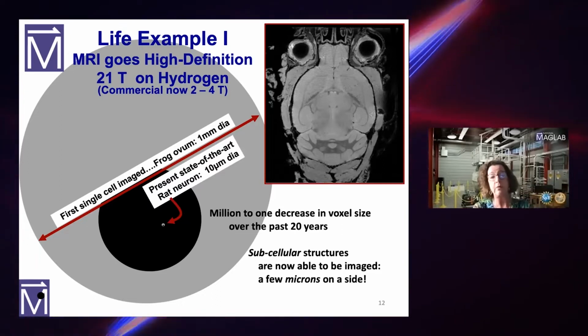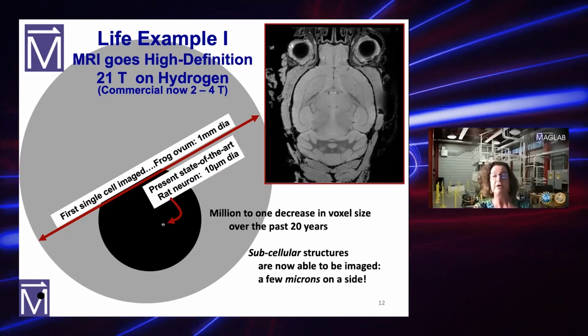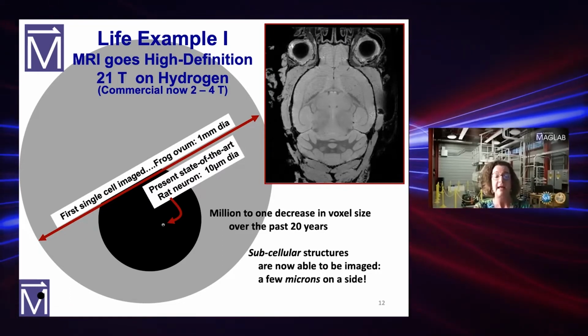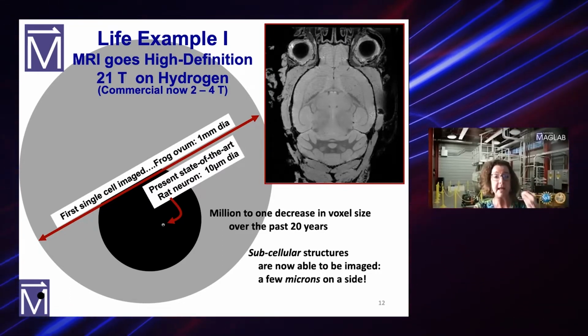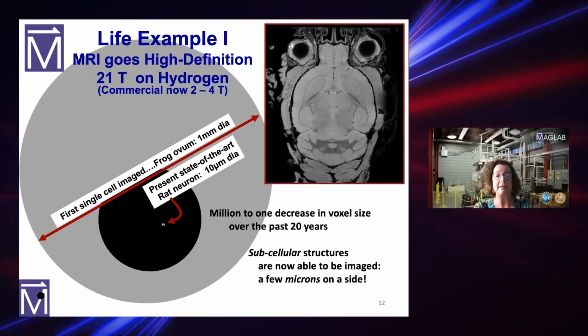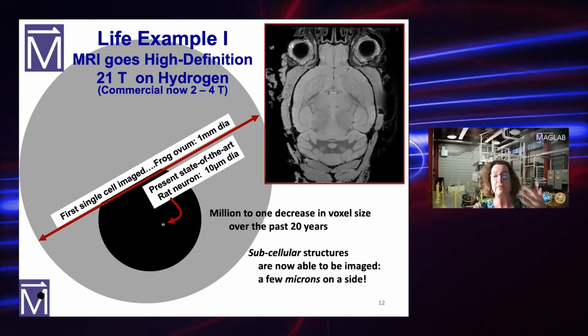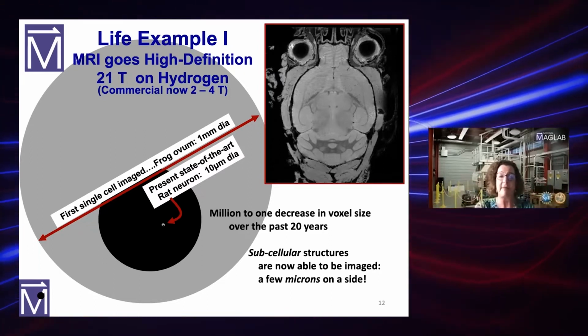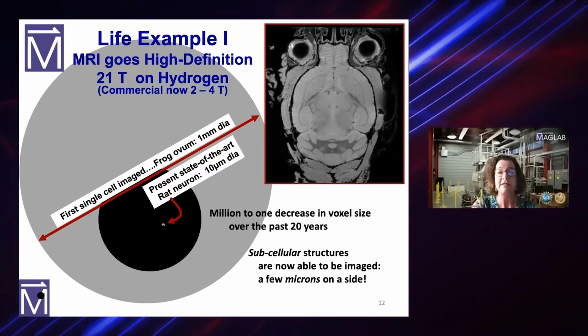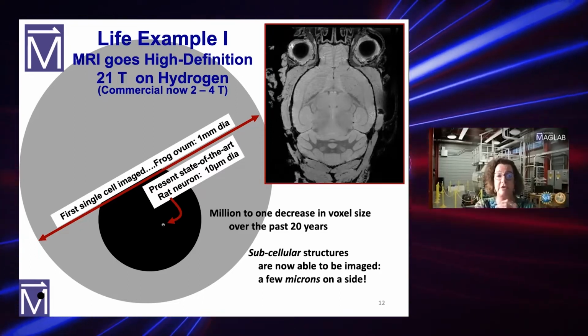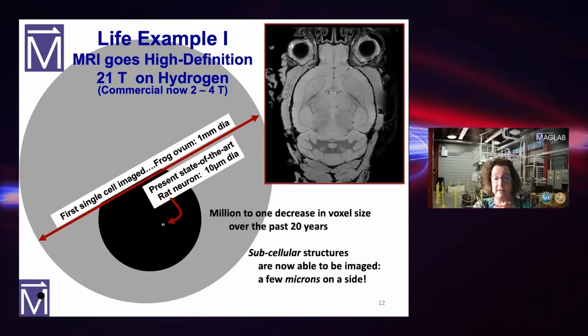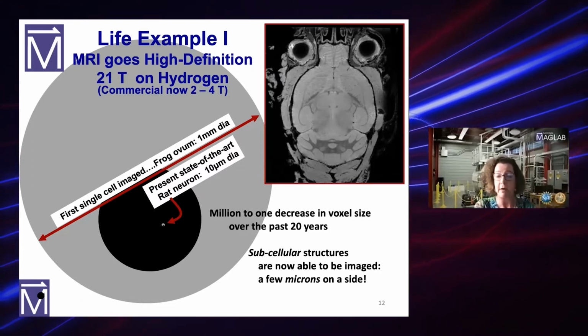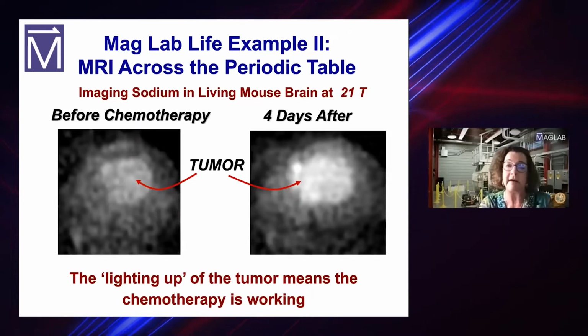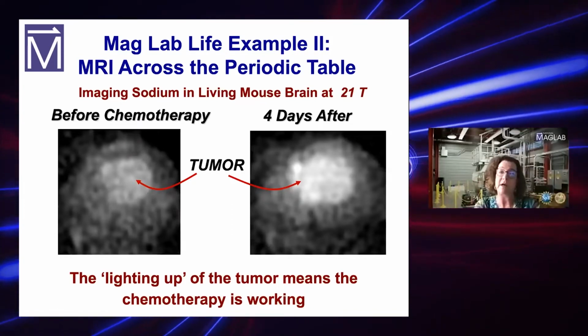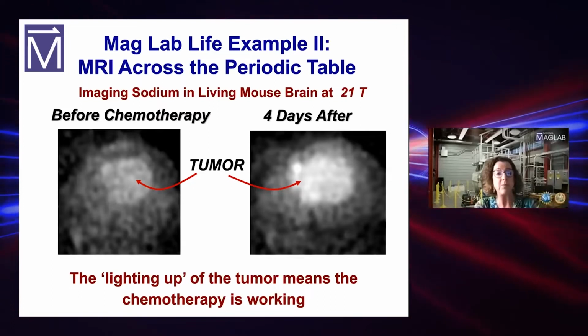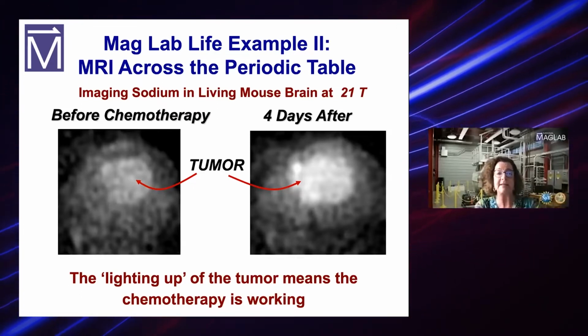However, as you know, when you are taking an MRI, you have a resonance condition between the field strength and the applied RF field. And measuring at 21 Tesla, the resonance frequency for hydrogen is really not good. It's not as bad as being inside of a microwave oven, but it's not that healthy. So we typically use 21 Tesla either to look at non-living things, like here's the skeleton of a frog, or we can look at other kinds of elements. So we call that unlocking the periodic table. Here's one of many, many examples of looking at sodium.